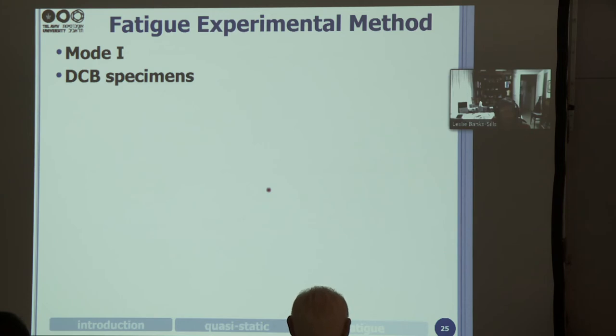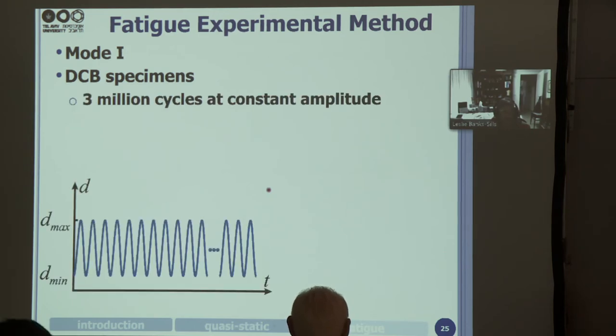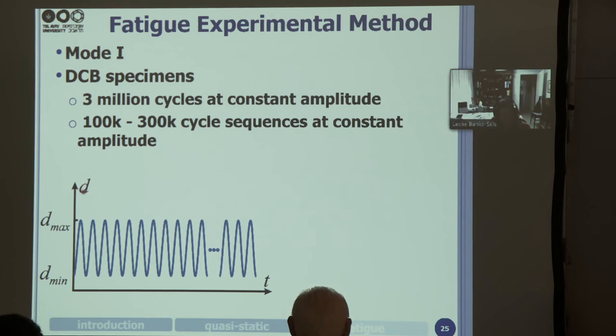We're in mode one with DCB specimens, and we carried out two specimens where we applied 3 million cycles at a constant amplitude, and these were displacement control tests. We also followed some work that's in the literature where we took one specimen and we carried out five sequences at a constant amplitude for 100,000 to 300,000 cycles. So we did two types of fatigue tests.